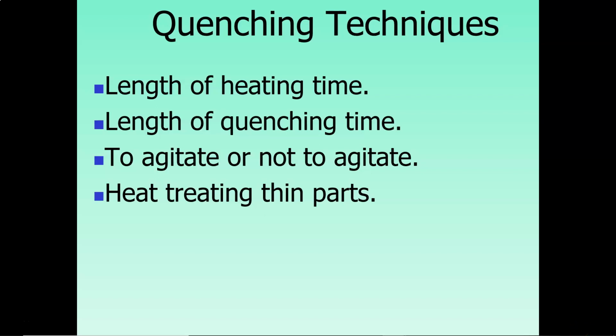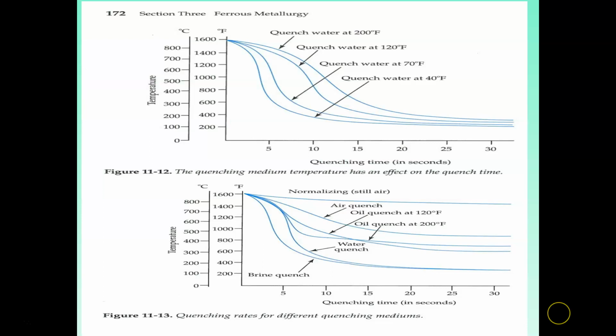Quenching techniques. A part should be left in the quenching medium until it can be safely cooled to the touch. Agitation should be utilized whenever possible to dislodge the vapor bubbles that can insulate the metal, causing soft spots, warpage, and cracking. To effectively heat treat thin parts or parts with thin webs, special protective heat treating clays can be utilized to protect the thin areas.